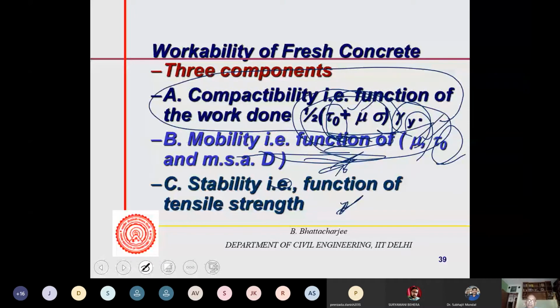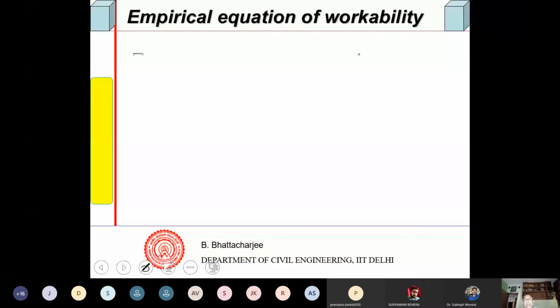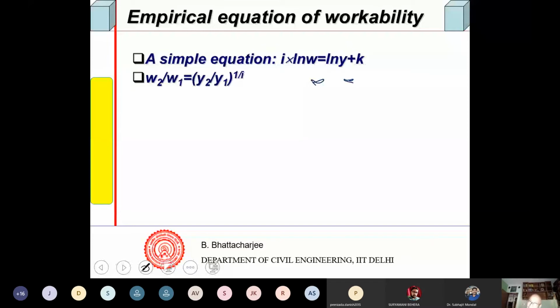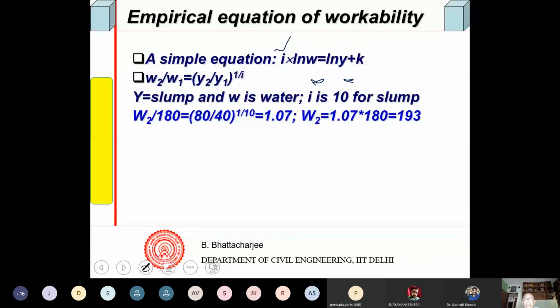So I should be able to actually model it, but at the moment we are not able to do that. There are some empirical equations. For example, one simple empirical equation is I into ln W, amount of water, equals Y, where Y is some of those empirical measures, plus K. A lot of people have tried a lot of empirical equations, and each equation varies from the other. There are 50 plus equations. They are in the book by Popovics, which I am mentioning here. Y is slump and W is water. I is 10 for slump. So this will be different for different methods used for measuring. For example, if you use compaction factor, this I value is different. If you use the VB test, it could be different.